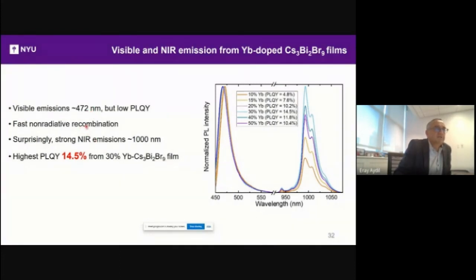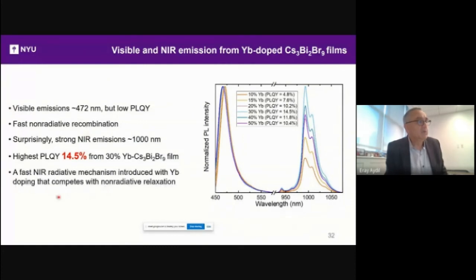So if you can get 14.5% photoluminescence quantum yield in the infrared with little visible emission, in the presence of non-radiative recombination which is very fast, that tells you that the transfer into the ytterbium ions is very fast and can compete with non-radiative recombination. So by putting in ytterbium, we introduced a fast near-infrared radiative mechanism that competes with that fast non-radiative recombination. And that's very encouraging because you expect quantum cutting to be very fast. So we have a new mechanism coming in. To show that it's exactly quantum cutting, we have to go above 100%, and that's what we're trying to do.